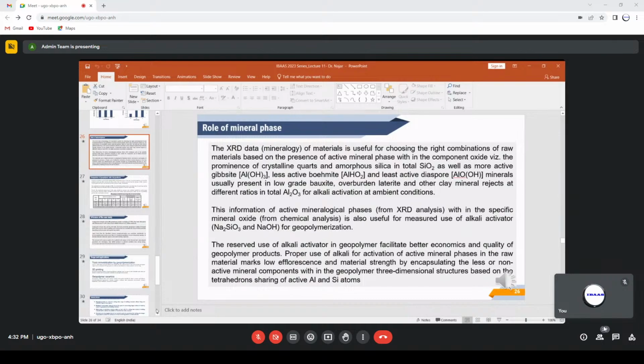This information of active mineralogical phases within the specific mineral oxide is also useful for measured use of alkali activator, that is a combination of sodium silicate and sodium hydroxide for geopolymerization. The reserved use of alkali activator in geopolymer facilitates better economics and quality of the geopolymer product. Proper use of alkali for activation of active mineral phases in the raw material marks low efflorescence and material strength by encapsulating the less or non-active mineral phases or components within the geopolymer three-dimensional structures based on the tetrahedron sharing of active aluminum and silicon atoms.